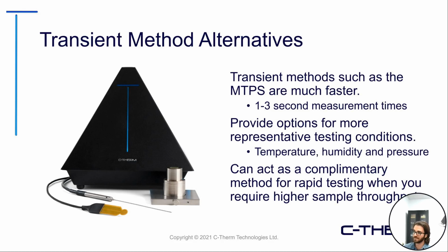And really, at the end of the day, these can act as a complementary method in tandem with some of these steady state methodologies. Because of the rapid testing aspect of transient methods, they lend themselves quite well to high sample throughput, where you're dealing with large sample volumes and you need rapid testing. Everyone knows time is money at the end of the day. So whether you're in the R&D stages, QA, or QC, these transient methodologies can be adopted to help speed up your screening process and find the materials that are generally more conductive or less conductive, depending on the end use application. And then later on down the road, if the industry standard requirements need C518 testing, then you can work with those in tandem.